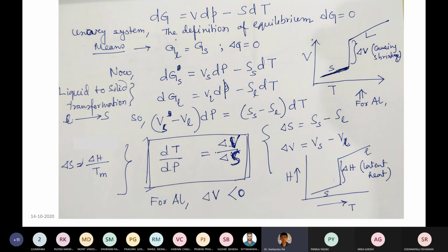So here, if you check, Vs minus Vl into dP equals Ss minus Sl into dT. Now, if you reorganize that properly, and we already know that delta S equals delta H by Tm, the melting point, this is the entropy at the melting point or phase transformation temperature. Then again, from this expression, you can directly get that dT by dP equals delta V by delta S, where delta S equals S of solid minus S of liquid, meaning entropy of solid minus entropy of liquid, and in the same way delta V is the change in volume between solid and liquid.